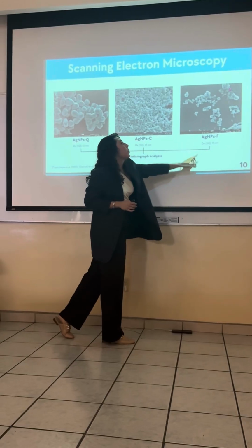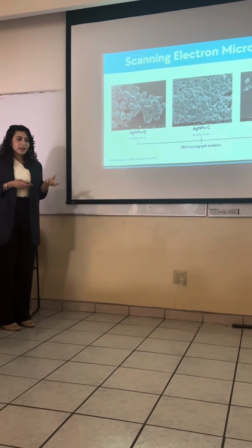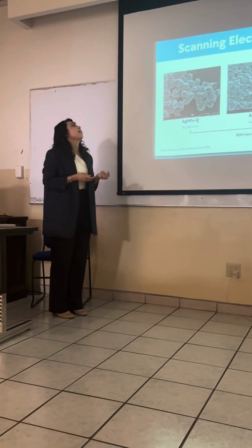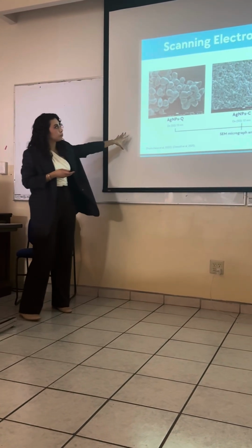And for determining the nanoparticle size, we did a SEM micrograph analysis, and we determined approximately, for the chemical method, a diameter of 13 nanometers, around 12 nanometers for the hot method, and around 11 nanometers for the green cold method. So why are we seeing this discrepancy in our results from the past analysis and this one?